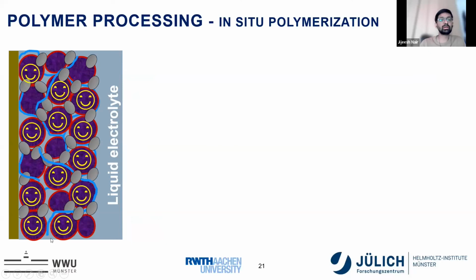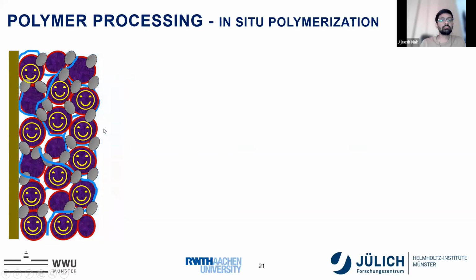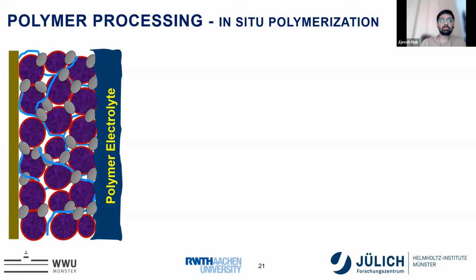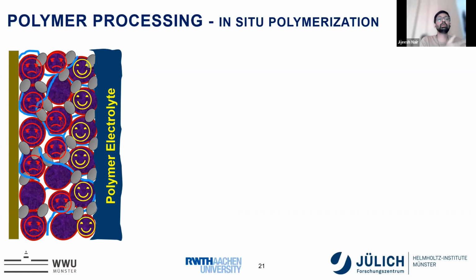This means that your electrolytes are happy and your active materials are happy, and lithium is reached everywhere. But when the liquid electrolyte is replaced with the polymer electrolyte, when we make it as a sandwich system, only the active material on the surface is in contact with the polymer electrolyte, whereas the bulk cannot be completely in contact with the lithium ions. This means that lithium can only transfer through the active materials. This slows down the reaction kinetics, reduces the active material utilization, and reduces the performance at a higher C rate.